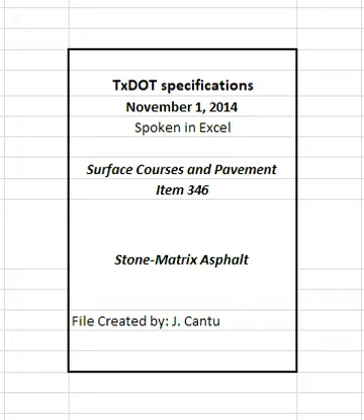Provide the engineer with the density profile of every sublot in the lot within 1 working day of the completion of each lot. Report the results of each density profile in accordance with Section 346.4.2, Reporting and Responsibilities. The density profile is considered failing if it exceeds the tolerances in Table 12. No production or placement payment adjustments greater than 1.000 will be paid for any sublot that contains a failing density profile. When a handheld thermal camera is used instead of a thermal imaging system, the engineer will measure the density profile at least once per project. The engineer's density profile results will be used when available.